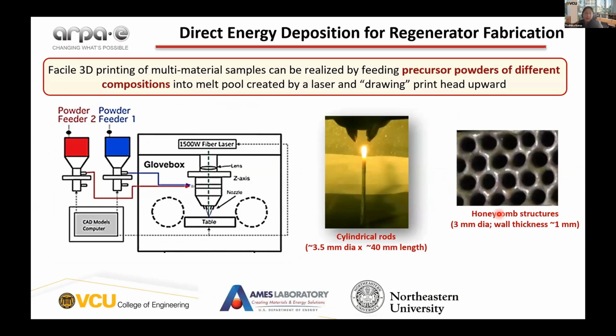The first is DED. DED is a little different from powder bed fusion and binder jetting in the sense that here powders are fed within a nozzle, and this allows us to make multi-material structures, because the precursor powders are deposited simultaneously into a melt pool created by a laser, and then we can draw the print head upwards. We've made cylindrical rods and honeycomb structures using this technique.